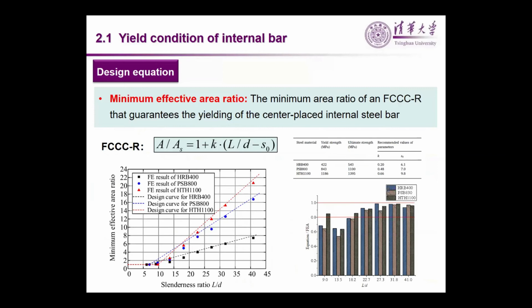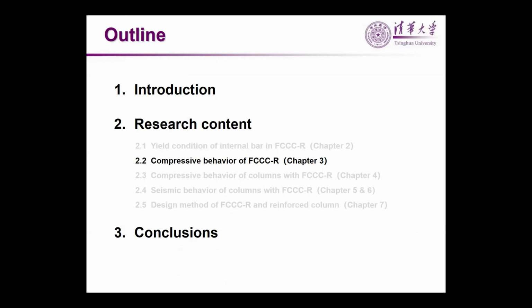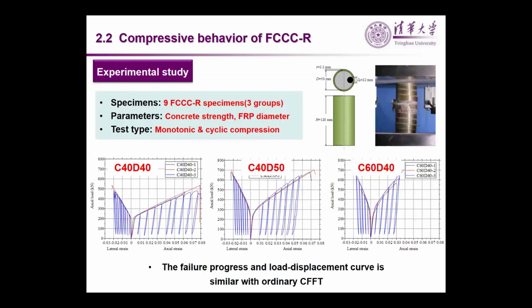Well, in the next chapter, the axial compressive behavior of FCCC-R is studied. Nine specimens are tested under either monotonic or cyclic compressive load, and test results indicate that the ultimate failure of the FCCC-R is controlled by the circular fracture of the FRP tube. And the load displacement curves of the specimen show a typical bilinear ascending behavior, which is quite similar to that of the ordinary CFFT, the concrete filled FRP tube. Well, in order to predict the compressive behavior of the FCCC-R,